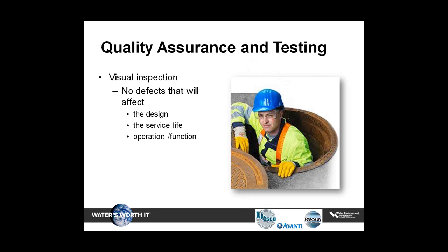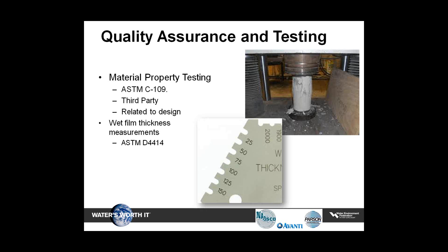All manholes shall be visually inspected. Any leakage into the manhole and areas where the systems were installed by the contractor shall be identified. ASTM C109 shall be performed on cementitious products. During the application, a wet film thickness gauge, meaning ASTM D4414, shall be used to determine thickness.